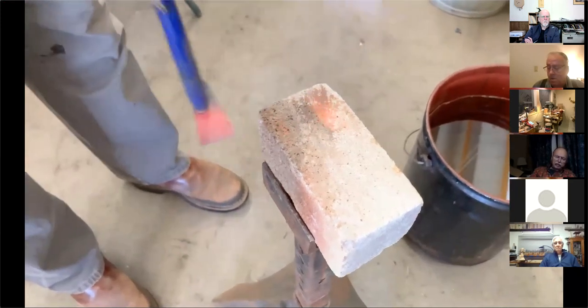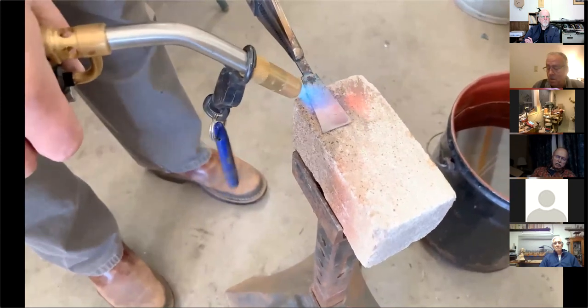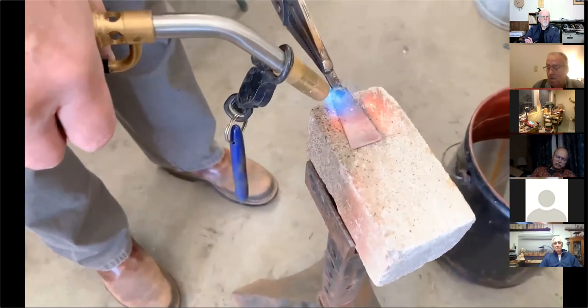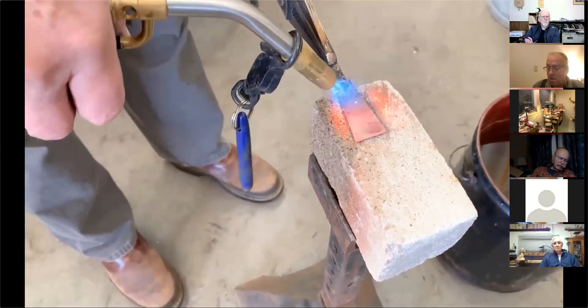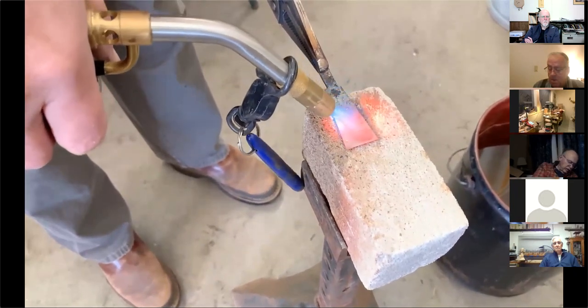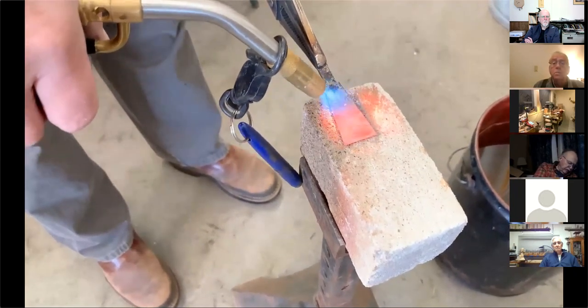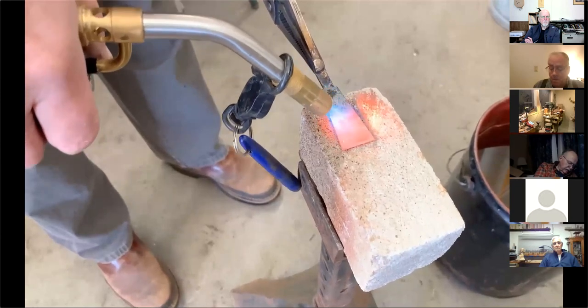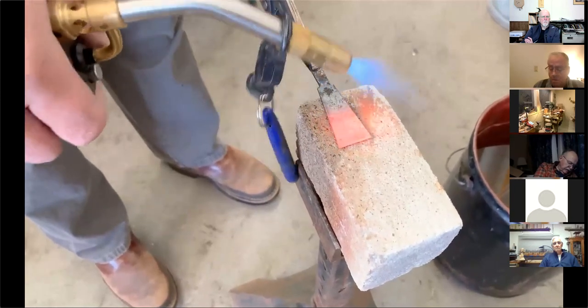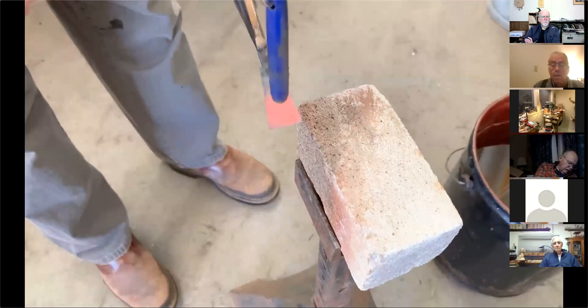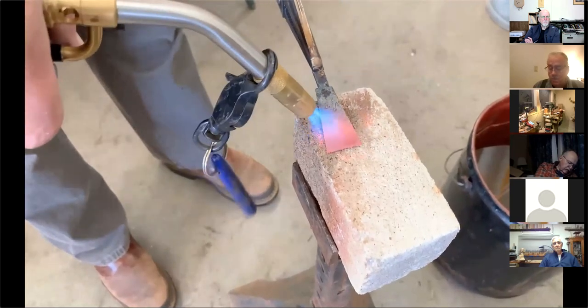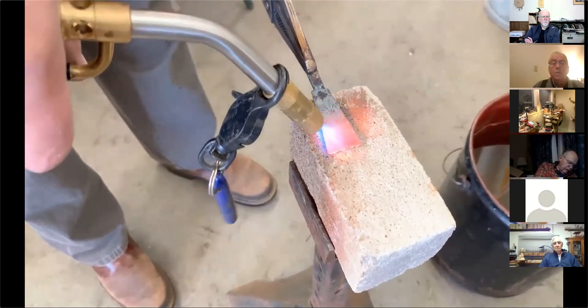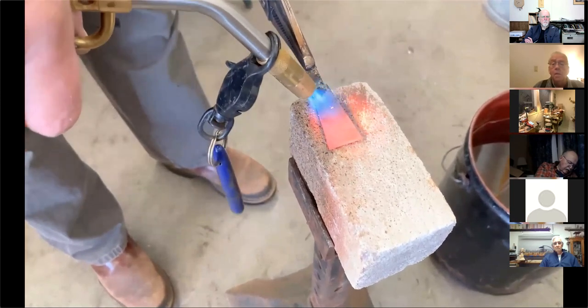That bucket behind it is a bucket of peanut oil. Any vegetable oil will be just fine, and that smells a lot better than used motor oil. And turn the blade over periodically so you're heating from both sides. This is about 90 thousandths thick. Now you see it's some red, but it's still magnetic.